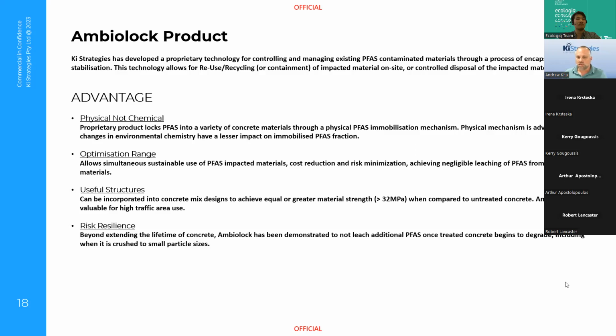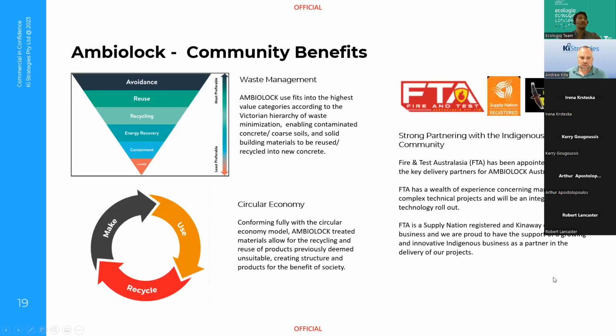But we have been able to successfully create sub-base materials that are many megapascals in strength. I think we had stabilized sand at close to 40 megapascals. Our 32 megapascal concrete mix has achieved results greater than 40 megapascals and extremely low permeability and water penetration results, which I'll talk about in a minute. Next slide, please, Joy.